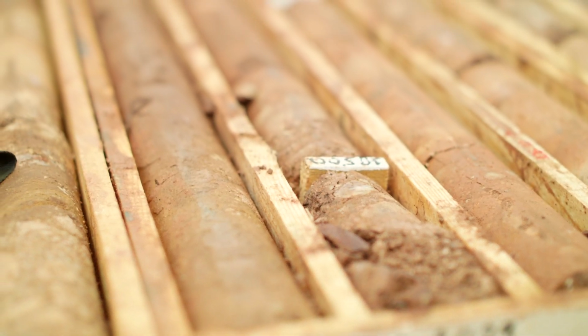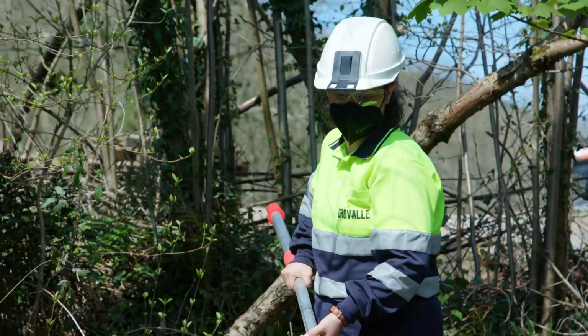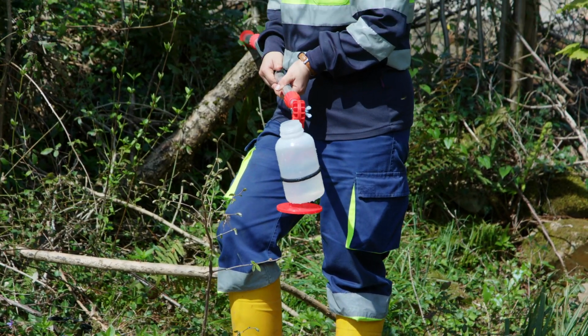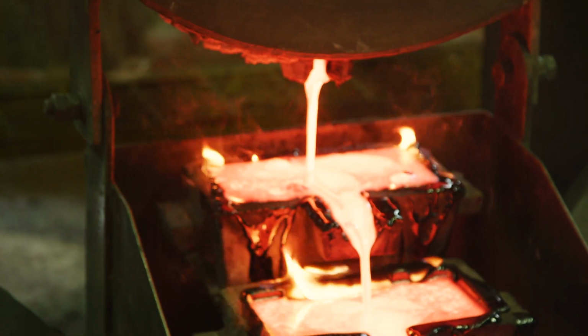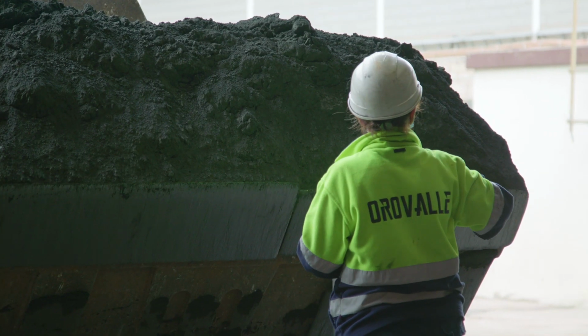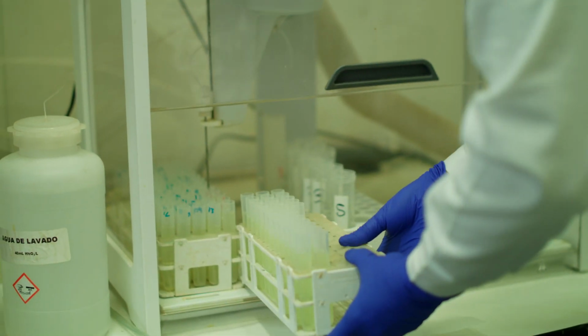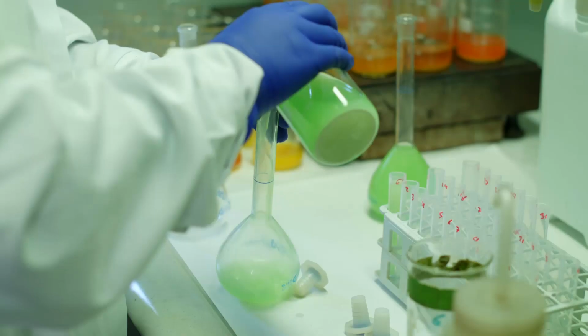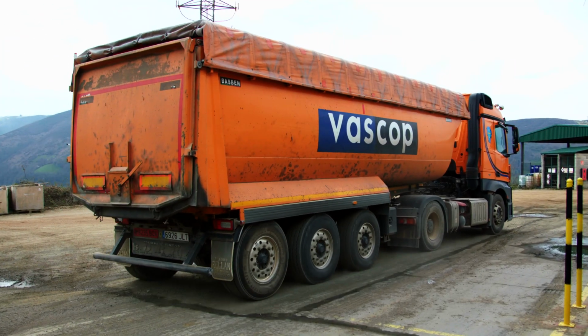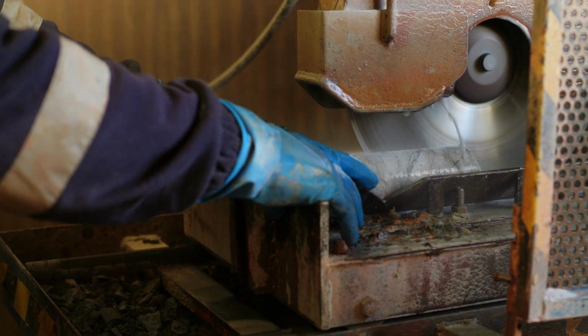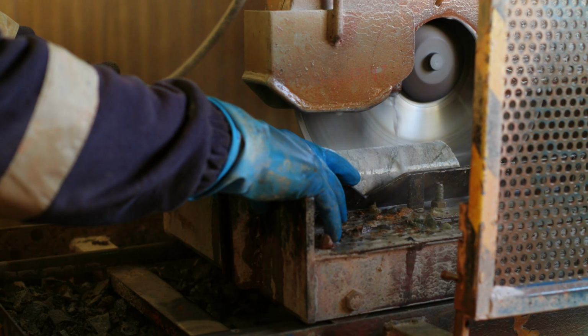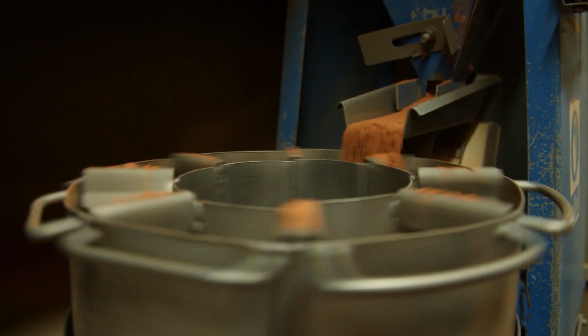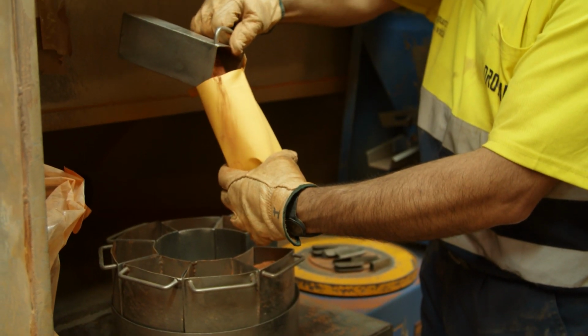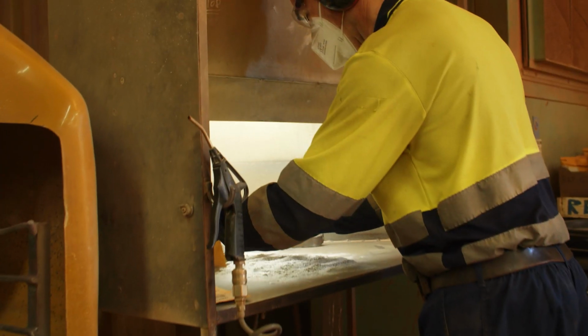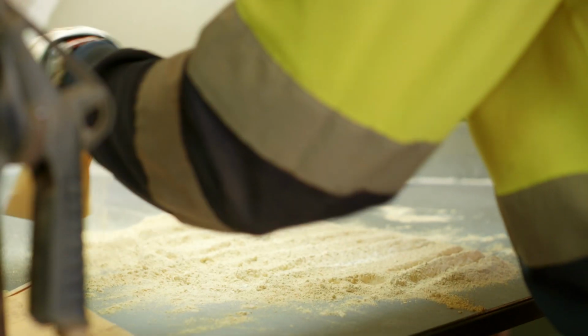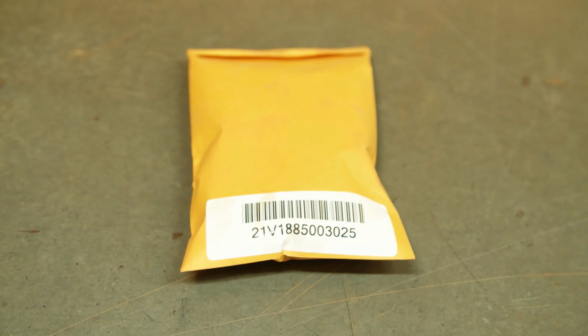obtained from exploration core logs, environmental samples for the control of water in the mine and surrounding area, samples of the final products for sale, bullions or doré bars, and copper concentrate. In this case, certificates of analysis are issued that must accompany our products from the moment they leave OroValle plant to their final destination. The samples first go through a technical preparation according to each type, where following different procedures, they are dried and ground to a particle size of less than 0.075 millimeters and are reduced to a weight of 150 grams without losing their capacity to be a good proxy for the whole sampling material being set aside.